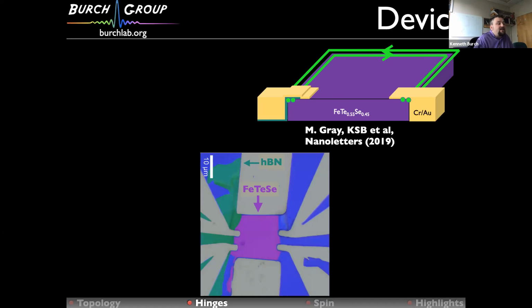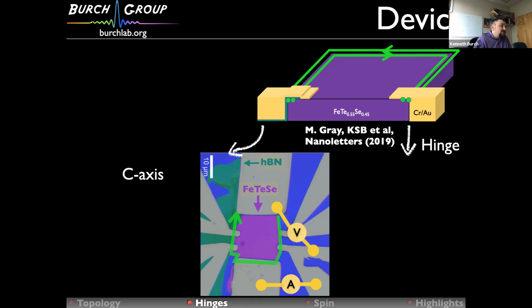Okay, so what I mean by that is we would apply voltage, say, from the point contact to one of the current leads, and then we would measure current from the same contact to a different lead. And then we, of course, check that as we played around, if we measured at different leads and so on, that we always get the same response. Okay, and the idea is that our point contacts on, say, the right surface, they're touching the hinge, and I'll show you the data there. And the contacts on the other surface, they go over the HBN, and so they should only be tunneling into the C-axis. All right. So what did we see?